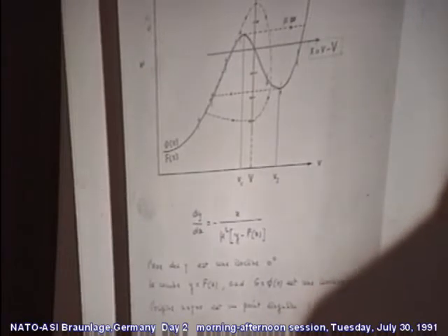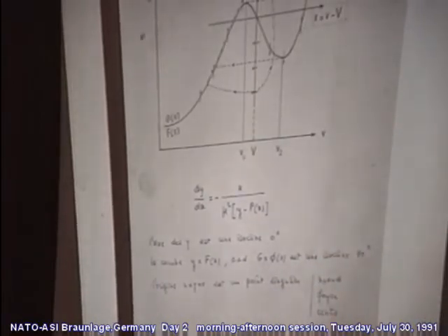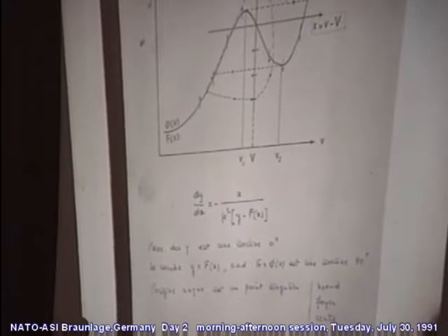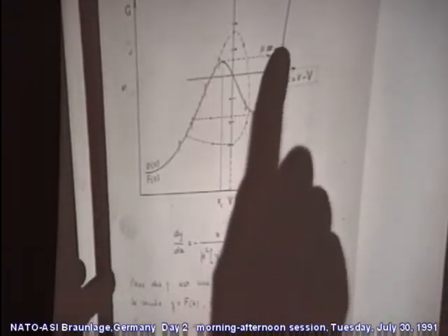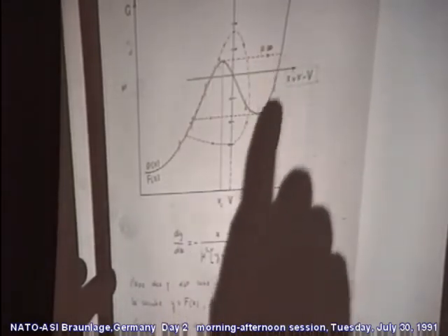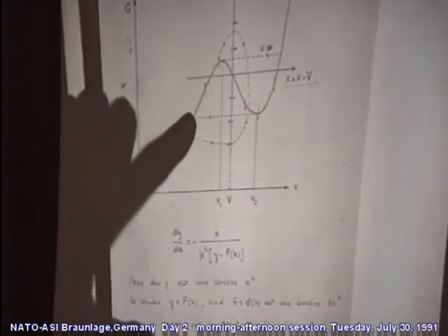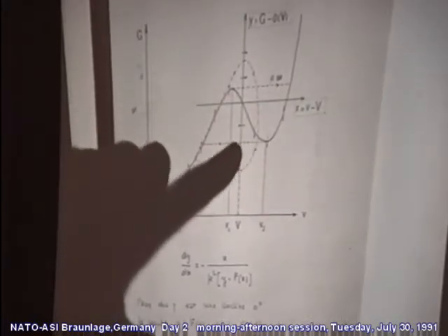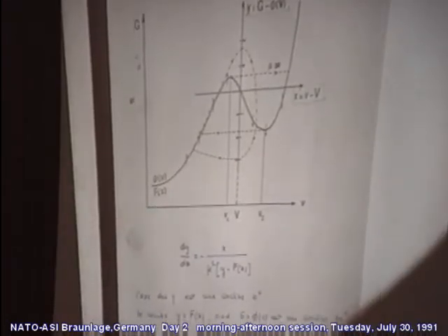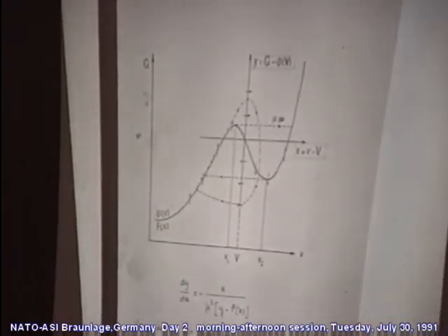And when the quantity mu tends toward infinity, that means that the inertia goes toward zero. And when the inertia goes toward zero, it is shown from this equation that the solution is this relaxation model we have studied before. So for small inertia, we have the relaxation model for zero inertia. And when the inertia becomes important, we have orbits in the phase space.